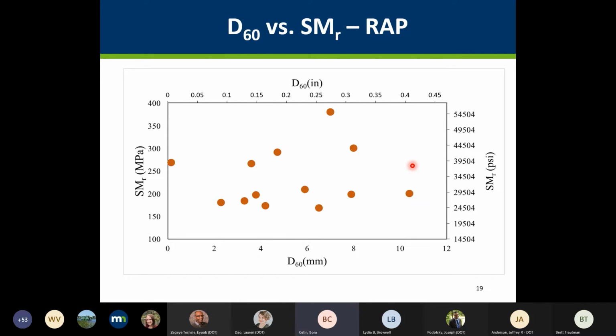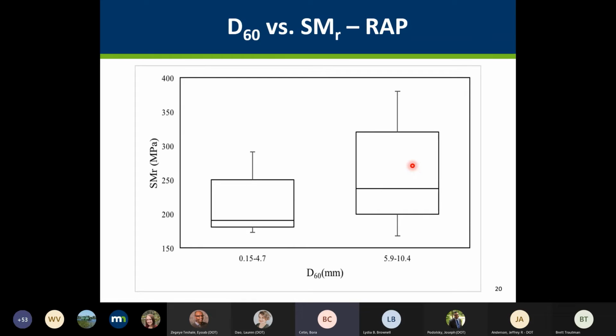And we did similar things with the D60 value from the gradation characteristics and tried to correlate that with the summary resilient modulus values, SMR, of the RAP materials. Again, you may not be able to see a consistent trend, so we tried to divide them into groups at different ranges. Here, basically, if your D60 value is within this range, you can assume a median summary resilient modulus of 180 megapascal for RAP materials. If the D60 value of your RAP is within this range, which is a wide range, then on the median value, close to 250 megapascal resilient modulus may be used as an input in your pavement ME analysis.